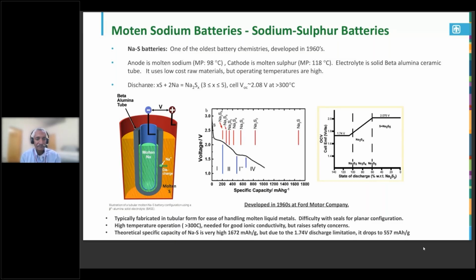This battery requires high temperature operation, at least close to 300 degrees C, because the beta alumina is a sodium ion conductor, but it requires a temperature close to 300 degrees C for the conductivity. At low temperature, it's not conductive. At those temperatures, sodium is molten because its melting temperature is 98 degrees, and sulfur is also molten. Melting temperature is 118. This beta alumina is typically made in a tubular form with a closed-end tube because it's easy to contain these molten metals inside.